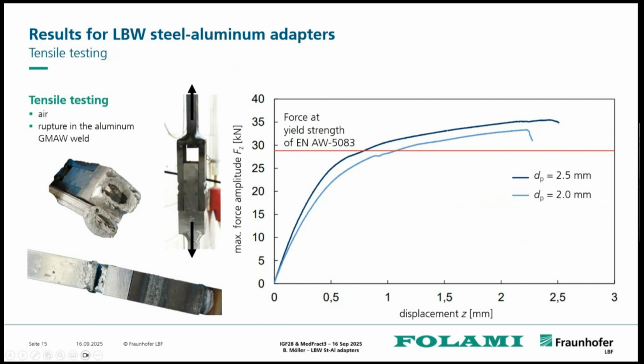So we have the steel part up here with a steel gas metal arc weld on the top, and the aluminum part down here with, I'm not sure, it could be a gas metal arc weld as well. We realized that our adapter is capable of reaching quite high force amplitudes, which are above the yield strength of the 5000 aluminum alloy, and having then a final rupture in this aluminum weld, so not in the adapter specimen itself.